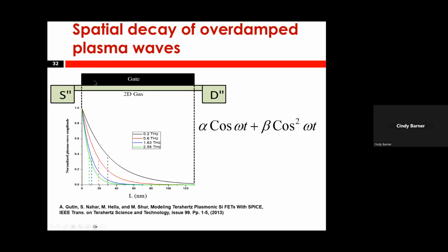And therefore you induce voltage between the gate and the source, and the gate and the drain, depending on the boundary condition, both are one. And as a result, there is this cosine-like variation of this voltage in time. But the device is non-linear, and therefore you have higher terms, cos squared, and this is positive, right? Always positive. Cosine squared is always positive. So you have a DC component. So as a result, you could use a transistor to detect radiation.